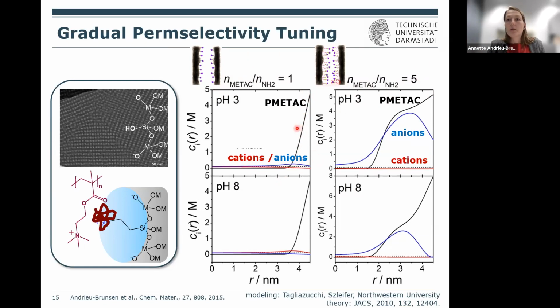And then you see two things. First, that the polymer or the chain length clearly influences the anion and cation distribution. And more interestingly here, you see from top to bottom the pH influence. And what you see here, if you have a certain chain length, is that not only the polymer, but still the pore wall matters, because if you change the pH, you still have remaining silanol groups in addition to the polymer. And these still influence the polymer, but as well the anion-cation distribution. And the anion distribution nicely follows the polymer distribution as well. So this shows you that even in these small dimensions, you have asymmetric distribution of ions along these pores. And this again is an interesting question, how this influences transport and how you can control this.